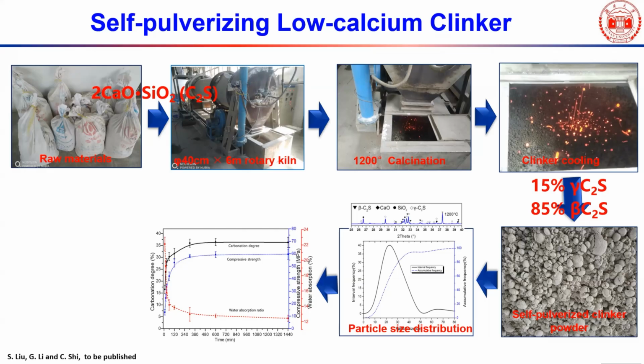And so, okay, we did some laboratory batches at Hunan Polytechnic University. You can see we used the material and the design as dicalcium silicate. And the tricky part is the cooling process. If we cool it very slowly, we get mainly gamma, beta or gamma dicalcium silicate, which has no hydraulic property, or cannot react with or hydrate with water. But here we try to control and get 85% beta dicalcium silicate. So later on, it will continue to hydrate with water and further enhance the property.